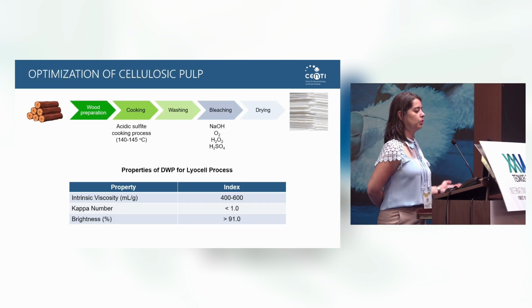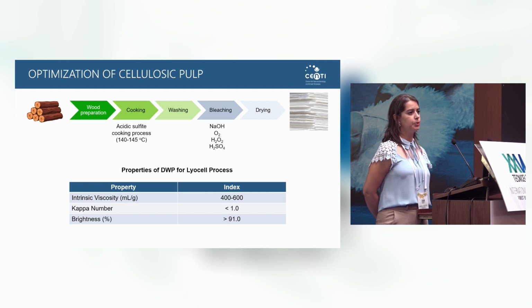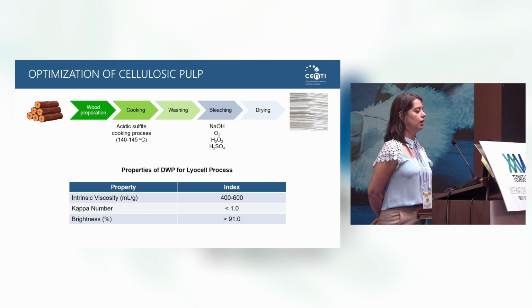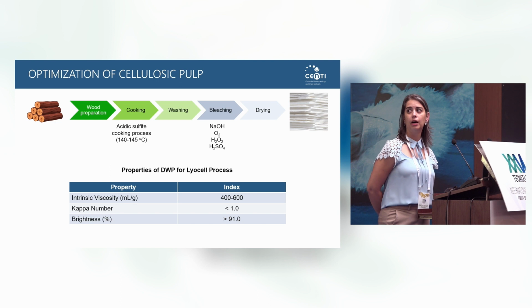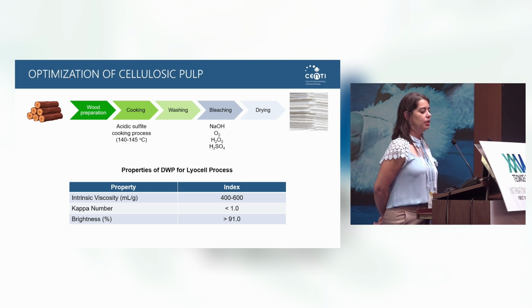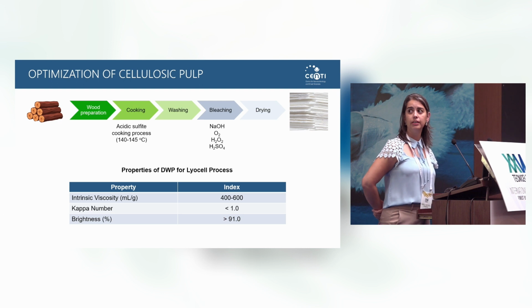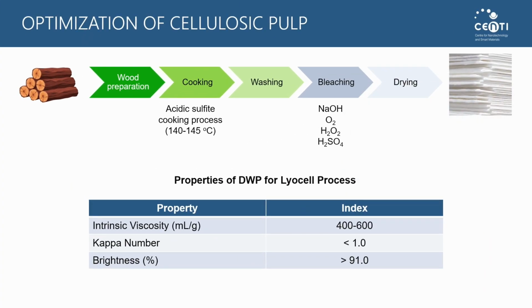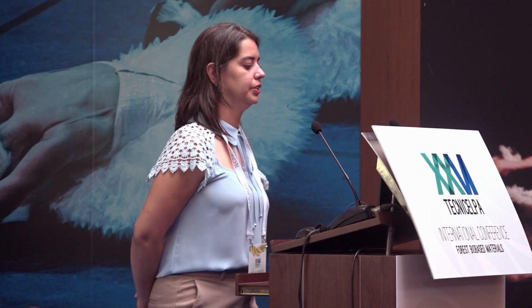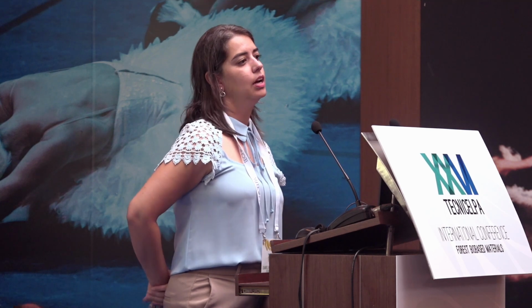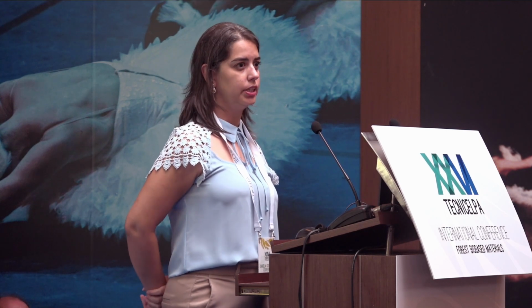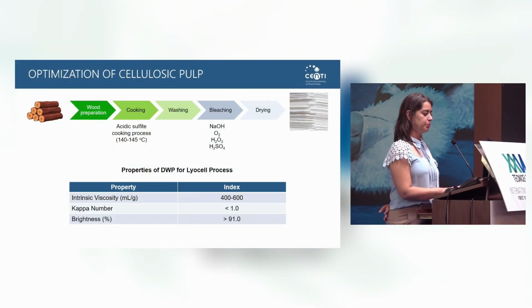The first step was the optimization of the cellulosic pulp. The acid sulfite process of Caima was optimized to get a dissolving wood pulp with characteristics appropriate for lyocell. So we have a low kappa number and brightness, showing that we have a high cellulose content, and also a short range of intrinsic viscosity that is optimum for cellulose fiber production.